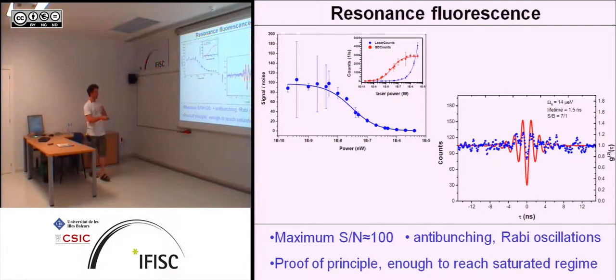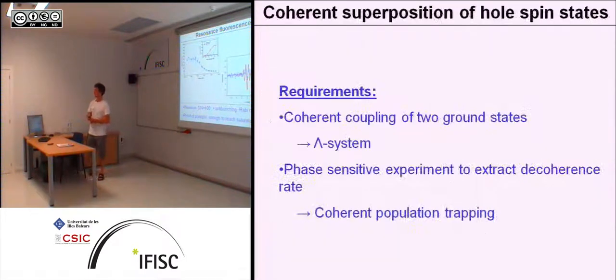What we also did is we were using this device to study the emission statistics of the quantum dot, and we can already see some hints of Rabi oscillations here and an anti-bunching dip in the middle. But the signal-to-noise ratio has to be improved by at least 2 orders of magnitude to really do quantum optical experiments with this setup. But we should be able to at least collect a resonantly excited state. So for quantum information processing, this system is good enough. But to really do quantum optics, like the Mollow triplet or something, we have to improve it by quite a lot.